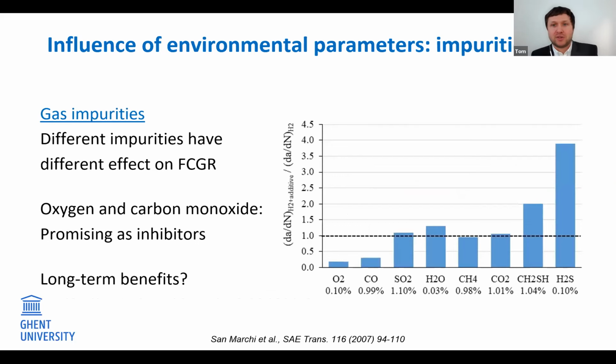Another factor is impurities. Addition of specific chemical gas components to a mixture of natural and hydrogen gas shows a lot of potential. Hydrogen gas purity strongly influences the uptake of gaseous hydrogen into a material. As such, depending on the specific gas species, impurities may increase, may have no effect, or may reduce the severity of hydrogen-induced degradation.